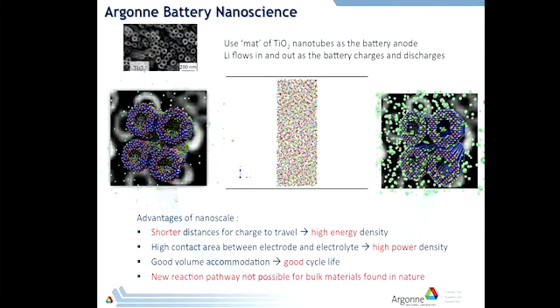And so some researchers at the CNM and the Chemical Sciences and Engineering Division here at Argonne came up with the idea of using a mat of titanium oxide nanotubes. So if you look at this, it's literally a lot of little tubes that are all standing up next to each other. They look a bit of a mess, and they're amorphous, they don't have a crystal structure. But what happens is that when you cycle lithium through them, the batteries get better. This is part of a lithium battery. It's the anode for a lithium battery.